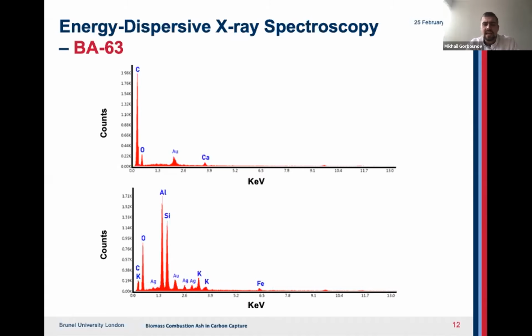Once a beam was aimed at the spherical particulate situated within our carbon, we can see a number of other species appear, as presented in the lower image. The analysis confirms that these spherical objects, as seen in the SEM, are of glassy origin, containing mostly aluminium and silica. Additionally, silver is also seen on the spectrum, but it is there because silver paste was used as the conductive adhesive utilized for this analysis. And just as with the fly ash, the peaks corresponding to gold are there to negate possible charging of the sample.